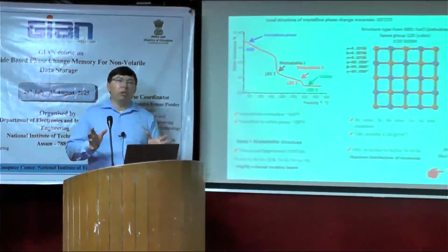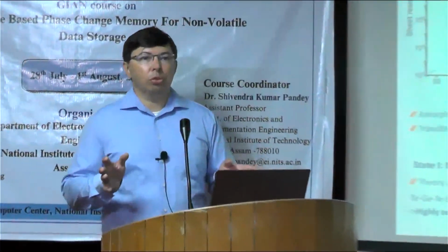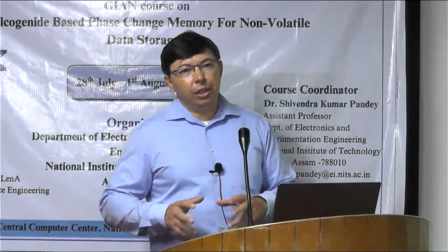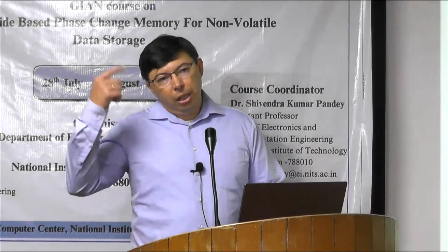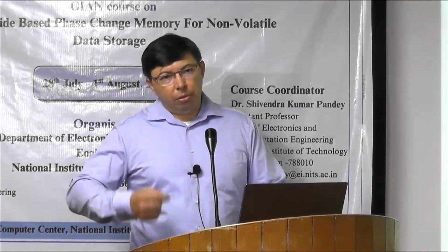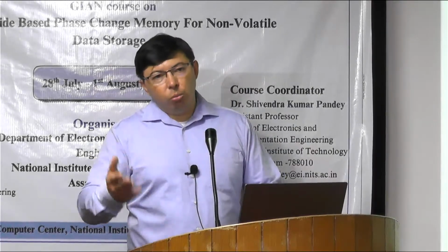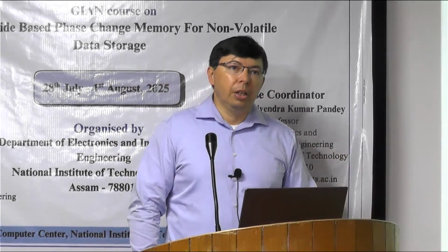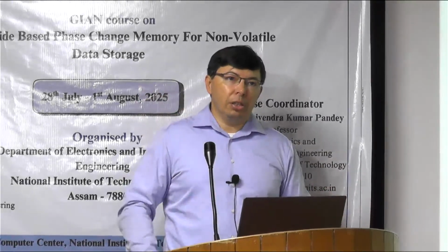We did some crystallization experiments with selenium. It also has a high crystallization temperature. Even at 200 centigrade, it's still amorphous, but after 300 centigrade, it's crystalline. So I think it's normal that you have amorphous and crystalline phases. So doping with selenium or arsenic increases it. This is another type of chalcogenide. They have a larger crystallization temperature.